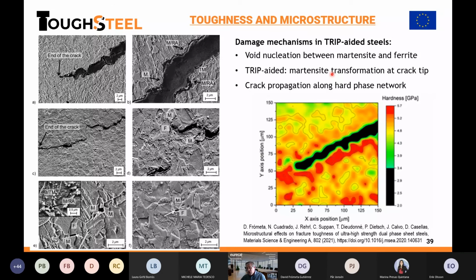If we look in more detail at the microstructure and how the cracks grow in these materials, we see that the retained austenite that transforms to martensite during the deformation produces martensite that contains higher carbon than the fresh original martensite, because retained austenite has been enriched by carbon during the quenching and partitioning process. And this high carbon martensite is more brittle than a low carbon martensite. So in a TRIP effect steel, when the retained austenite transforms to martensite, it produces a more brittle net of martensite that guides the crack and eases its growth. So in TRIP steel, the propagation of the crack is along this hard phase that is harder than in non-TRIP steel, because of this brittle martensite. This is a picture of the crack, and this is the measure of hardness by indentation, and you can really see that the crack is growing toward the high hardness martensite.